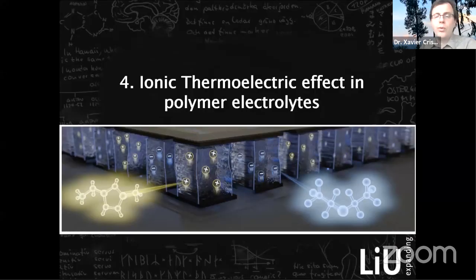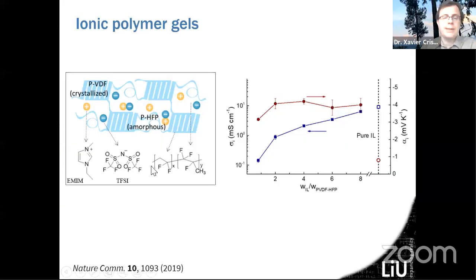So the material that we are using is this material—it's a polymer, actually a copolymer based on PVDF. It's a fluorinated polymer which has a crystalline and an amorphous phase, basically. These materials look like a solid polymer, and you can put ionic liquids into it, meaning they can swell with the ionic liquid.